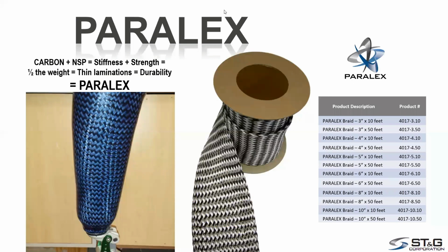Now, if you recall the testing graph of the Paralex, remember that the curve looked exactly the same as carbon, but it took more energy to make it fail. So this is a combination of weaving the NSP and the carbon together, and you get your I-beam stiffness from both of them. The nice thing too is you'll have the impact resistance of the NSP, but you have the stiffness of the carbon. As you can see, it comes in different widths and different lengths.